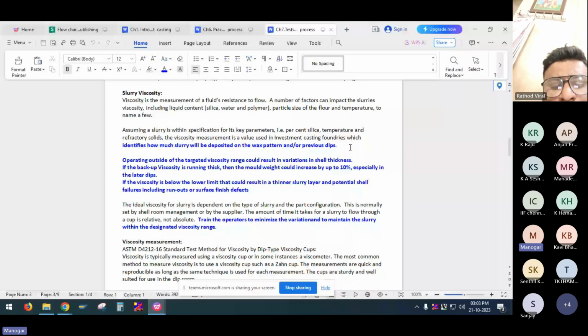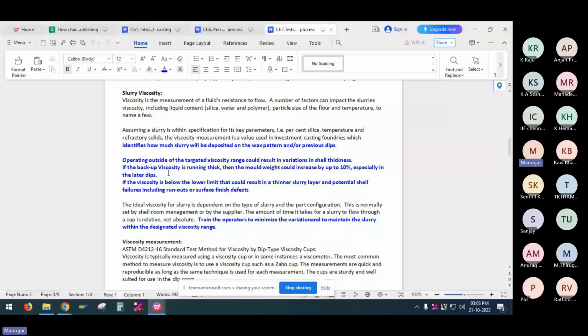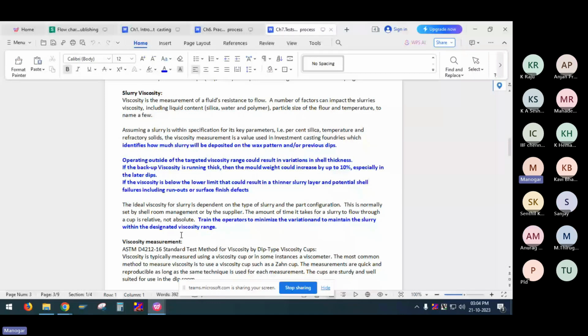Operating outside of the target viscosity range could result in variation in shell thickness. If the backup viscosity is running thick, then the mold weight could be increased by 10%, especially in the latter dips. If the viscosity is below the lower limit, that could result in a thinner slurry layer and potential failure, including runouts, surface finish defects, or cracks or failure while pouring. So viscosity control is a must in the investment casting process. And we have to train the operators to check the viscosity in a proper way to avoid any variations while they are measuring, so that they are controlling within the range.